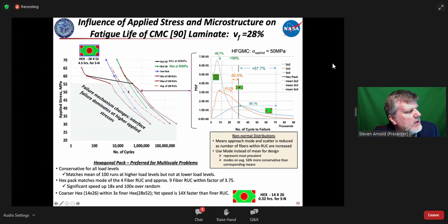But what's interesting to me here is at any given load level, we're able to actually predict the distribution of the fatigue life. That's a function of various instances of the microstructure. So we've run 100 different instances here. The blue is coming from a 4 fiber RUC. The orange is from a 9, and the gray is 25 fiber RUC.